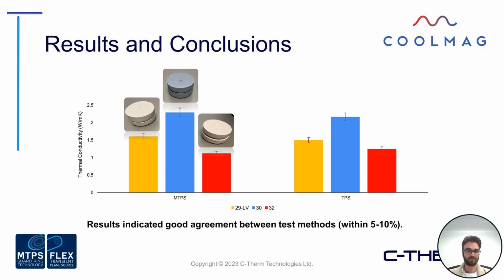So what we did in this example here is really we just compared MTPS to TPS measurements on these different sample types. I like this data set because one, it shows some varying thermal conductivity ranges, from about 1 watt per meter Kelvin up to a little bit above 2, but it also shows the type of comparison that you can get between different methods. Different options out there do have certain considerations, but in many cases you can get some very comparable data between different testing options. So looking at the MTPS data compared to the TPS here, really good agreement within about 5 to 10% across the board. And again, just an example of a basic measurement using TPS bulk mode for the data presented here.